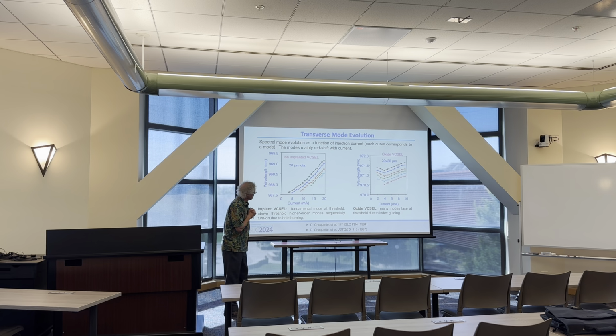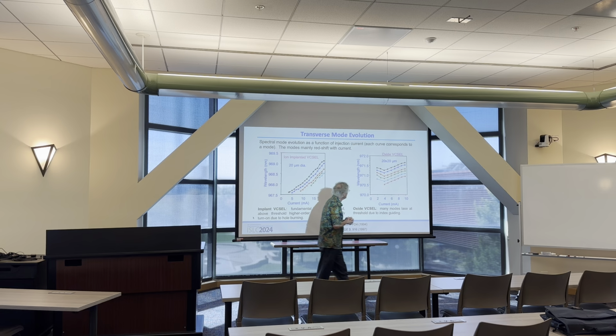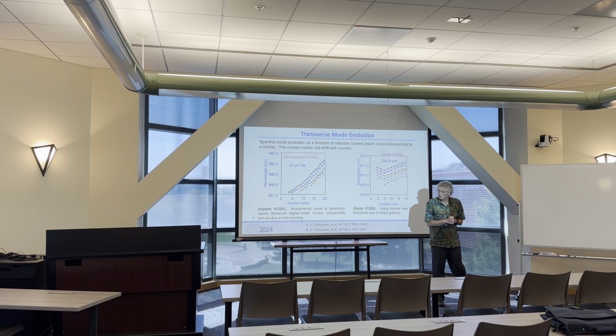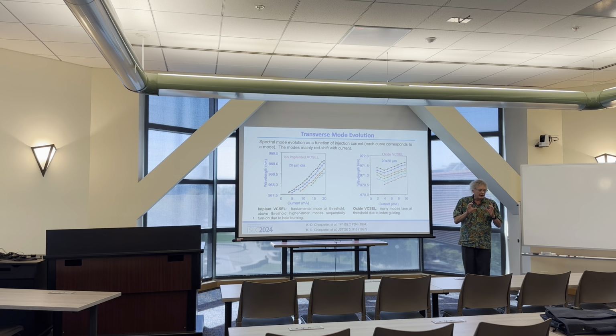Now, conversely, if you look at the oxide VCSELs made from the same structure, they have very different modal behavior. Then at threshold, a bunch of modes all just turn on at once. And this is indicative of that index confinement that is inherent from that buried oxide.